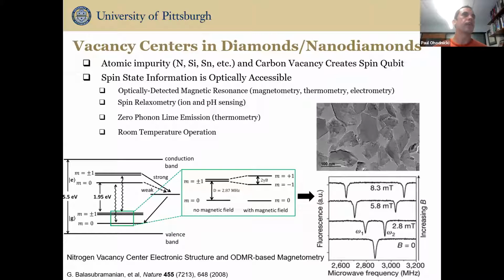So in the case of vacancy centers in diamonds and nanodiamonds, there's a number of different techniques which are used to get information about the spin states within these materials. One of the most common is the optically derived or optically detected magnetic resonance-based techniques. These are very well known for measurements of magnetic fields. This is because of the splitting of the spin states associated with the application of a magnetic field due to Zeeman splitting. And this shows, for example, how we can measure fluorescence.